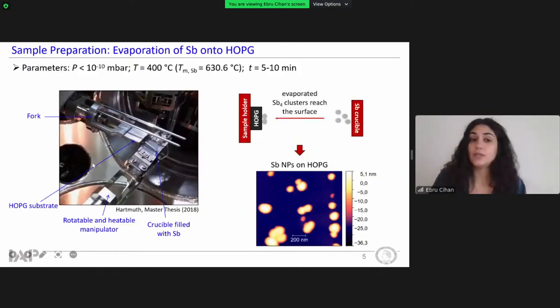For this, we chose antimony nanoparticles because from our previous experiments, we know that we obtain amorphous antimony nanoparticles as a result of thermal deposition in our ultra-high vacuum chamber. And we also know that it is theoretically possible to convert the amorphous antimony to crystalline antimony by heating. So for this purpose, we first produce our antimony nanoparticles in our ultra-high vacuum chamber by thermal deposition, and then we transfer the sample to the atomic force microscope without breaking the vacuum for further manipulation experiments.